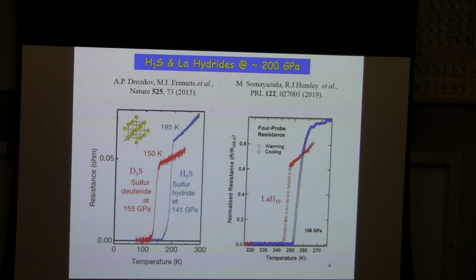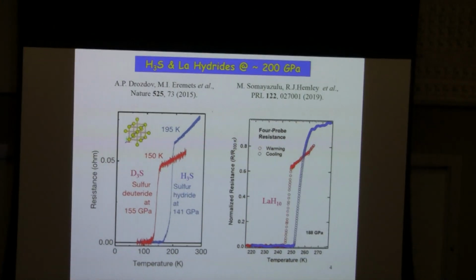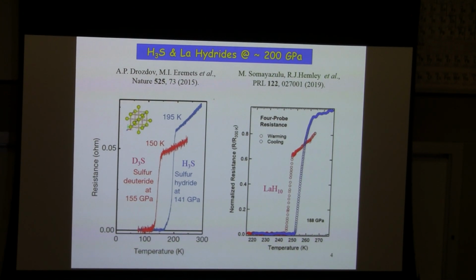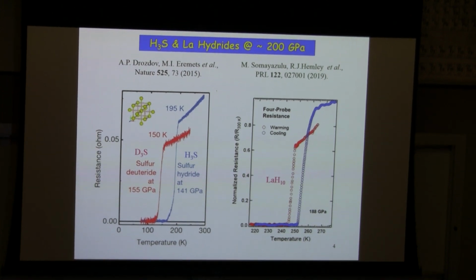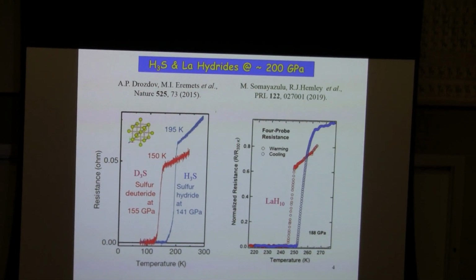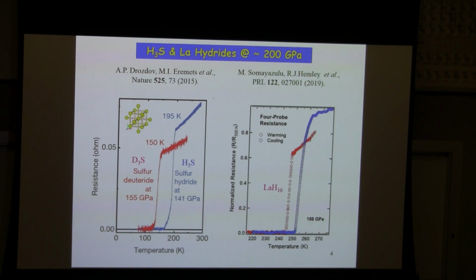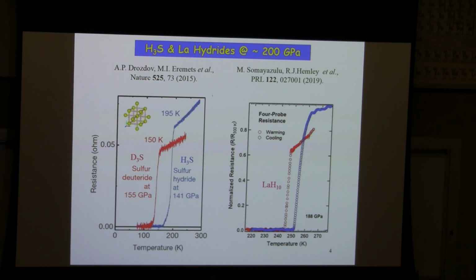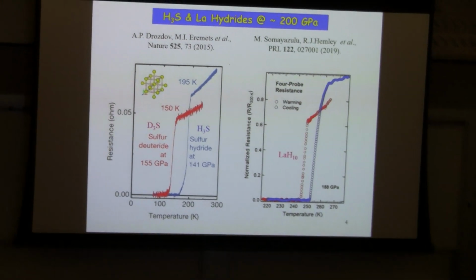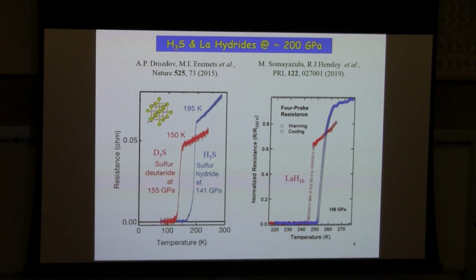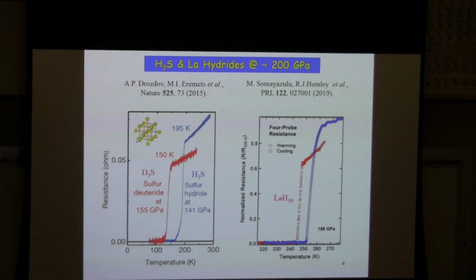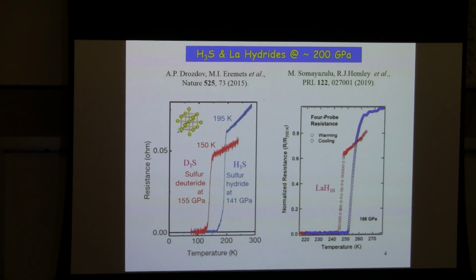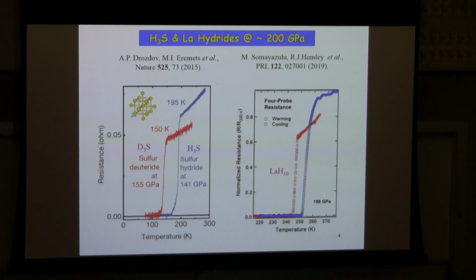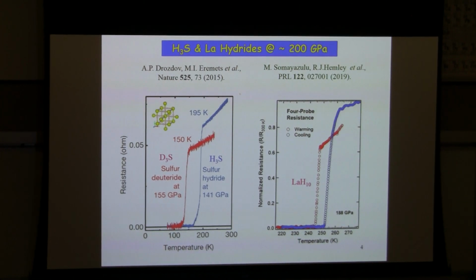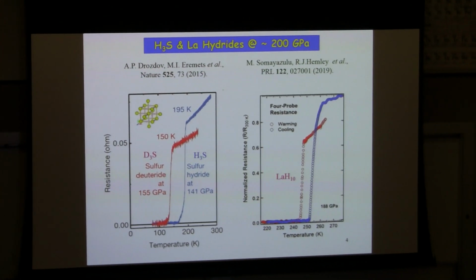But you may wonder how high this pressure scale is. 200 GPa is quite a huge pressure, like well inside the Earth. Or in other words, if you imagine a 1 cubic centimeter solid, when you apply 200 GPa pressure, the volume shrinks to almost 1/5. So 200 GPa is so huge a pressure, because the volume shrinks to only 20% of that at ambient pressure, that everything will change under such a high pressure. So in that sense, it's not surprising.